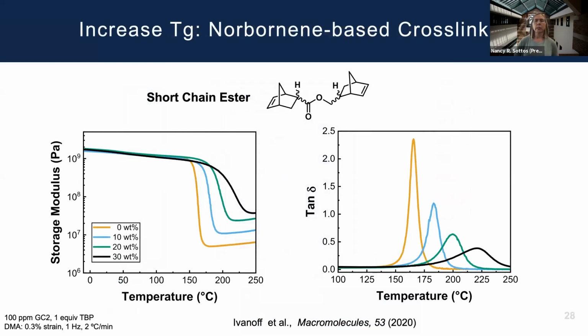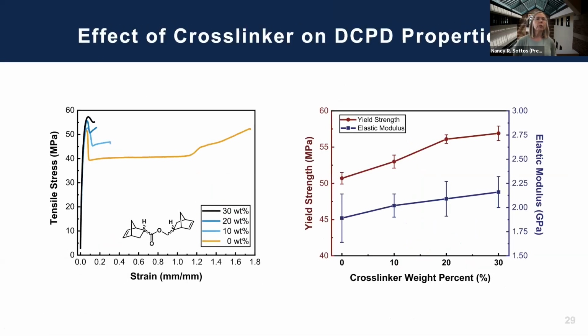So the first thing is the increase in the glass transition temperature, and this work was just published last year. And what we stumbled into was working with these short chain esters, these norbornene-based crosslinkers, by adding different concentrations of this crosslinker into our DCPD resin. You can see by these DMA curves that the rubbery modulus is changing quite a bit, as well as the glass transition temperature, indicating that we're getting increased cross-linking. And as you can look from the peaks in the tan delta, we're pushing the TG out from about 160 C without any crosslinker to, at the highest concentrations of crosslinker, up to 220 degrees C. And that actually, I think, is quite remarkable that we're getting a 220 glass transition temperature, again, on a desktop with very simple molding and very small amounts of energy input.